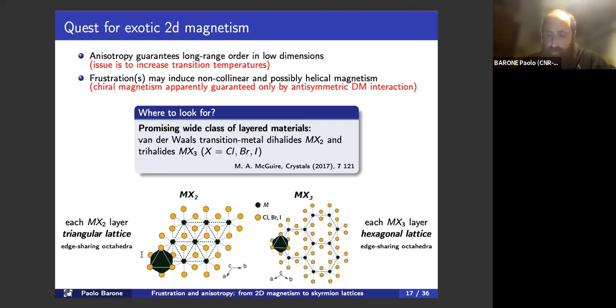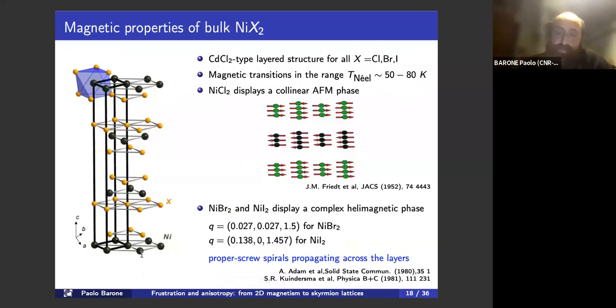We focused on a specific subclass of this material, which are the nickel-based ones. This is because this class of van der Waals magnetic materials has been known since the 50s. And here is shown the bulk structure. In the bulk, they have a relatively low critical temperature, below 100 Kelvin, but this is typical of this class of material.